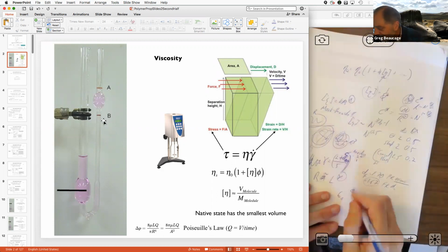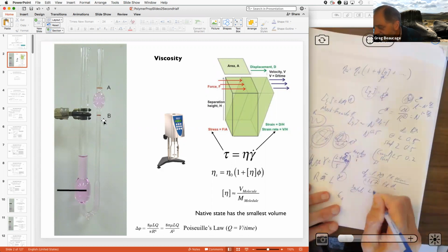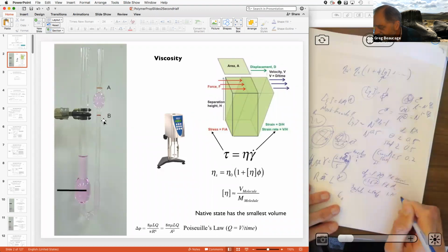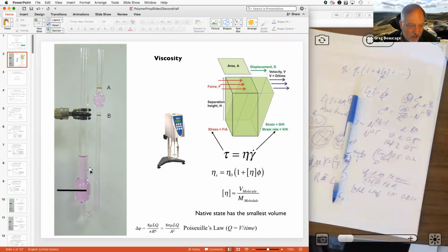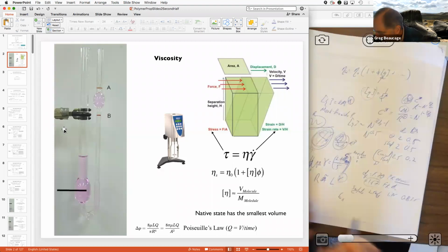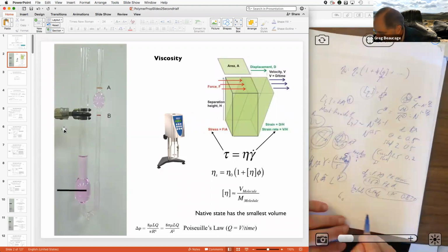So say concentration is 5 mg per ml, then you get 2.5 and you cut it in half. And you get 1.25, and maybe you get 0.875 or something, whatever that ends up with, right? And you can cut it again. So you do like 1, 2, 3, 4, 5 cuts on that, where you keep adding in equal volume of solvent to dilute it down. So you have to measure the amount of material you put in at the beginning, so you can do the dilutions to get the concentrations.